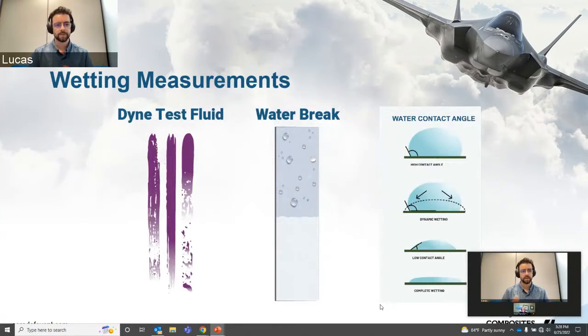So let's talk wetting measurements. These are the most deployable in manufacturing. They're literally the easiest to use. Traditionally, you'll see dyne tests done a lot in, I'll just say, polymer processing, like film processing and molding. Dynes have been around forever. Inks have different surface tensions. You paint them on the surface and count to 5 and watch if they bead up or wet out a little bit. And you try to get an indication of what the surface energy of the part is.